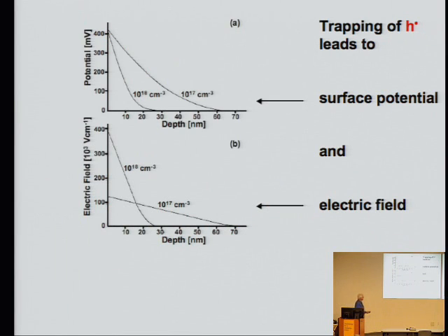Now these voltages, surface potentials, can be calculated. This is a paper that we wrote in the mid-80s. And there's a surface potential calculated for a flat surface of a dielectric medium filling half space. And this concentration of charge carriers, this is 10 ppm, this is 100 ppm. So 1 out of 10 to the 5 or 1 out of 10 to the 4 of the oxygen atoms carries such a hole charge carrier. And you get about half a volt, 400 millivolt. And that value is only a function of the dielectric contrast between your solid and the air or vacuum. In this case, calculated for a dielectric constant of 10.